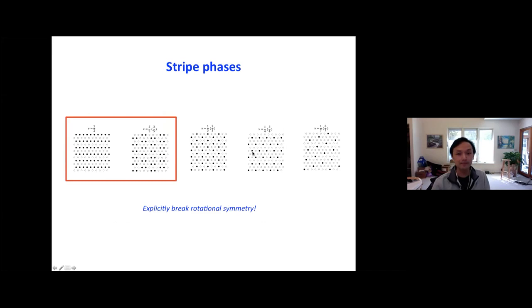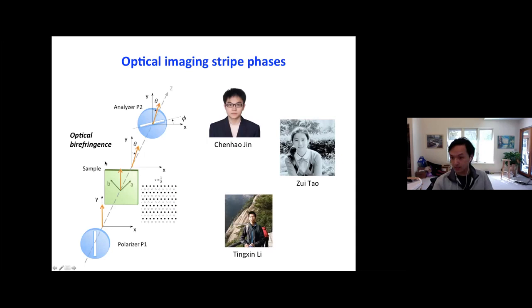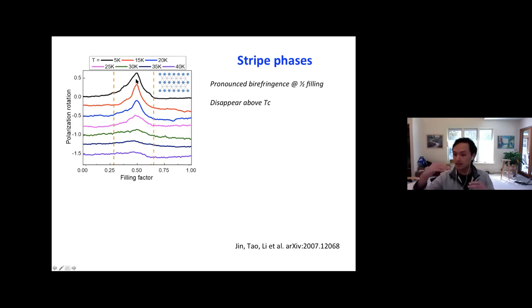Very quickly, you can also see that some of these states break rotational symmetry spontaneously because of the competition of short range and long range Coulomb interaction. We look at the polarization rotation, because if the state breaks rotational symmetry and you send linearly polarized light into the system, it will rotate the polarization of the light, right? It's called optical birefringence. And you can measure this polarization rotation angle as a function of filling factor. Indeed, you can see a peak in the rotation angle at 1/2 filling, which is the place you expect a strong stripe phase. And this is expected. The rotation quickly dies away with filling factor away from 1/2 filling.